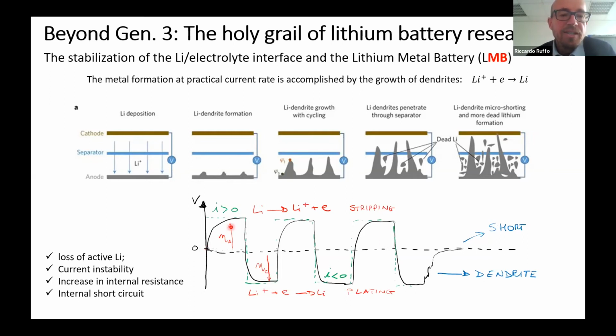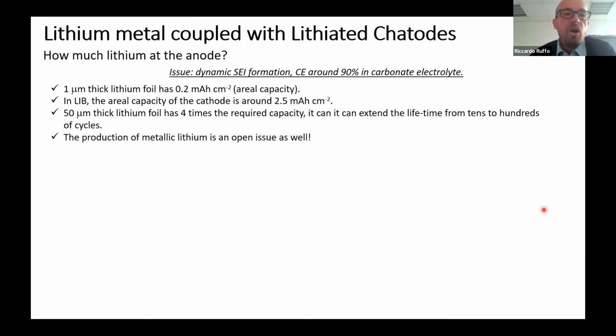So if you look at the curve of stripping of the lithium, consuming of the lithium, and plating of the lithium carefully, sooner or later you will get these current instabilities due to the formation of dendrites and then short circuits due to the contact of the anode material with the cathode material. But let's make a couple of calculations about this metallic lithium.